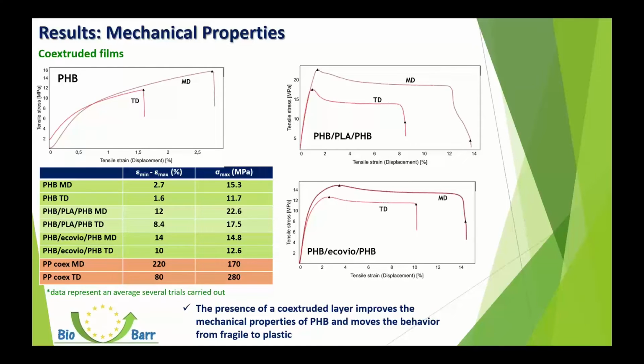These are instead the results obtained for the co-extruded film. Even if, as you can see, the presence of a co-extruded layer improved both the values of elongation at break and tensile strength of PHB, these values are still very far from conventional polymer used in flexible packaging, like for example, co-extruded polypropylene. The fact is that the presence of the co-extruded layer changed the behavior of the PHB from a fragile behavior to a plastic behavior.